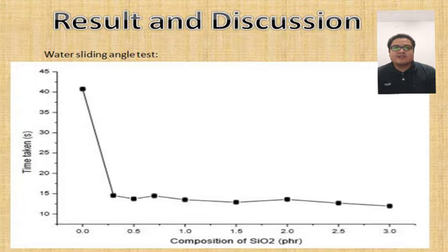This mobility can be related to lower surface energy on the coating. Lower surface energy reduce the attractive force between the coating and water molecule. This phenomenon can be related to the silicon dioxide non-polar properties, as non-polar molecule is an excellent compound for repelling water. Thus, the addition of silicon dioxide improves the hydrophobicity of palm oil polyurethane.